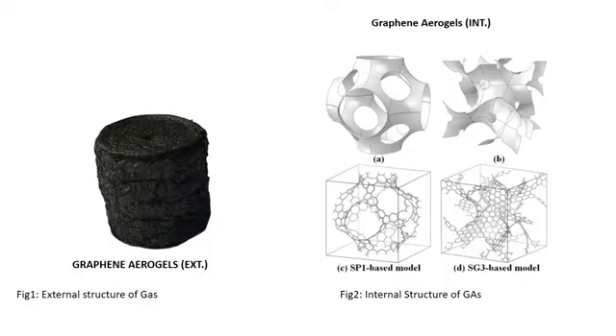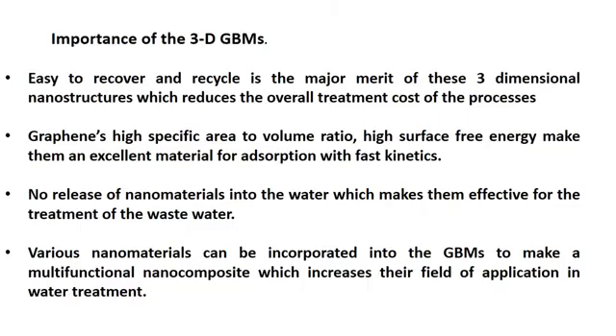Here is the external and internal structure of the graphene aerogel. Regarding the importance of 3D GBMs: easy recovery and recycling is the major merit of these 3D nanostructures, which reduces the overall treatment cost. Graphene's high specific surface area to volume ratio and high surface free energy makes it an excellent material for adsorption with fast kinetics. There is no release of nanomaterials into the water, making them an effective device for wastewater treatment. Various nanomaterials can also be incorporated into the GBMs to make a multifunctional nanocomposite, increasing the field of application in water treatment.